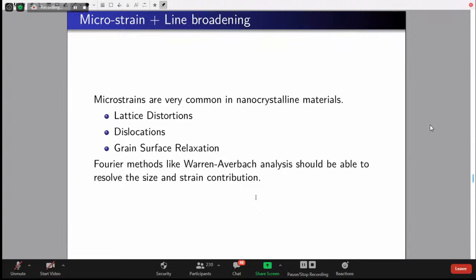Whereas the lattice distortions, which means let us suppose we lost one atom, then the lattice is distorted. If we have an extra atom coming, then the lattice is distorted. When I say lattice distortion, it means your D-spacing has increased or decreased. So these are going to give us again peak broadening as well as peak shifting. So these two things we have to see together.